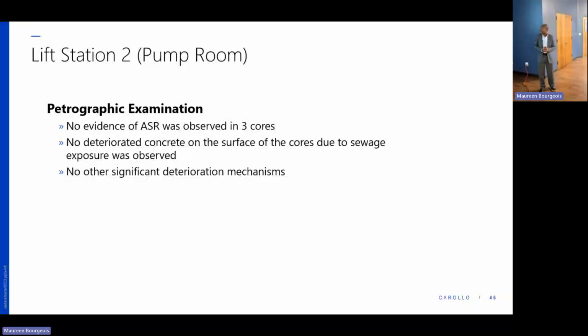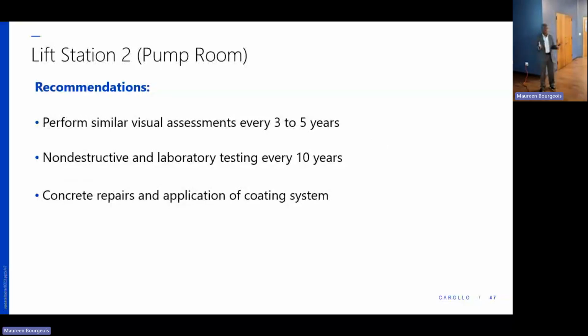So recommendations: every 3 to 5 years, a visual assessment, just like we did, to see if anything is changing from these structures. And then we also recommend an in-depth analysis every 10 years. And then in the areas where we described the efflorescence and the minor cracks, we want to go in and fix it. We described the areas whereby the sewage is probably affecting it, just like the wet well, and we want to go ahead and apply a coating system when we do this work. And our recommendation is in the next 3 to 5 years.